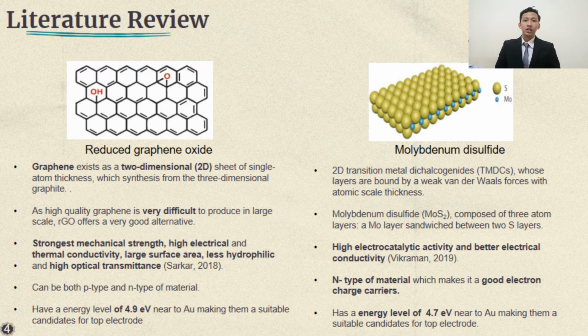Molybdenum disulfide is a 2D transition metal dichalcogenide whose layers are bound by a weak van der Waals force with atomic scale thickness. Molybdenum disulfide is composed of 3 atoms and it has a high electrocatalytic activity and better electrical conductivity. This material is an N-type material, which makes it a good electron charge carrier. It also has an energy level of 4.7 eV near to Au, making it a suitable candidate for top electrodes.